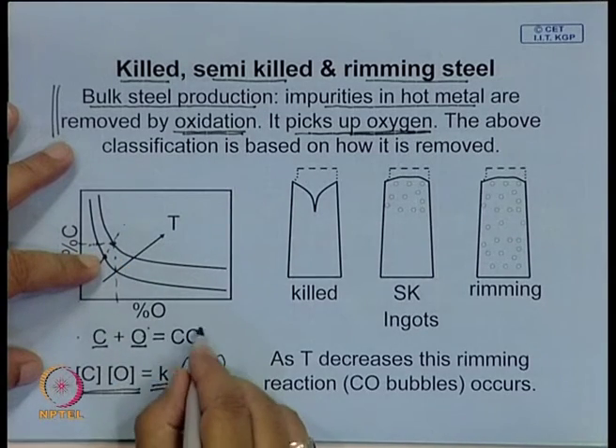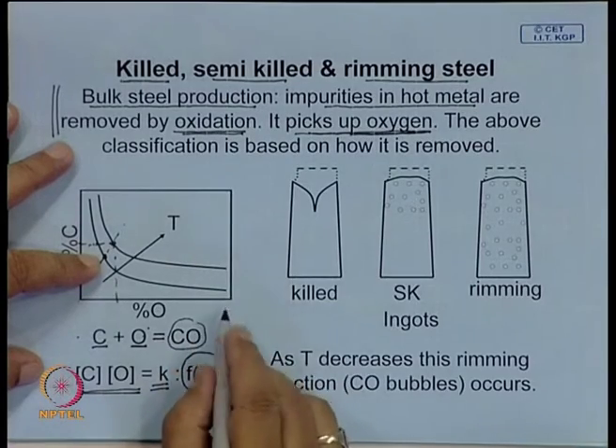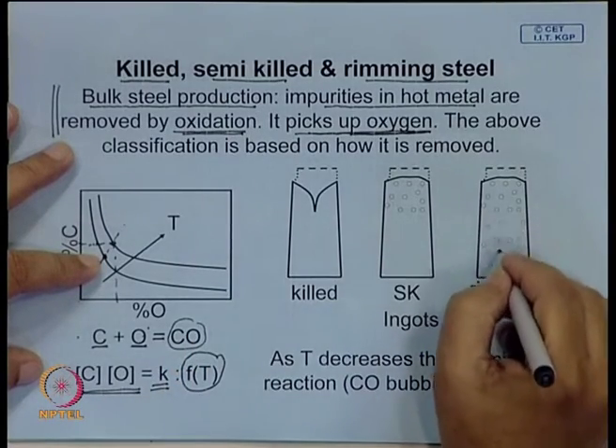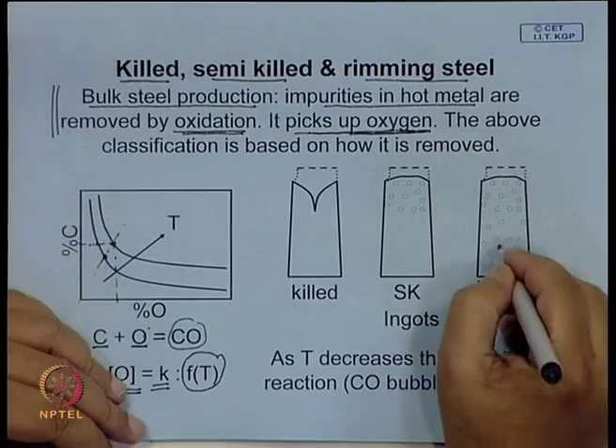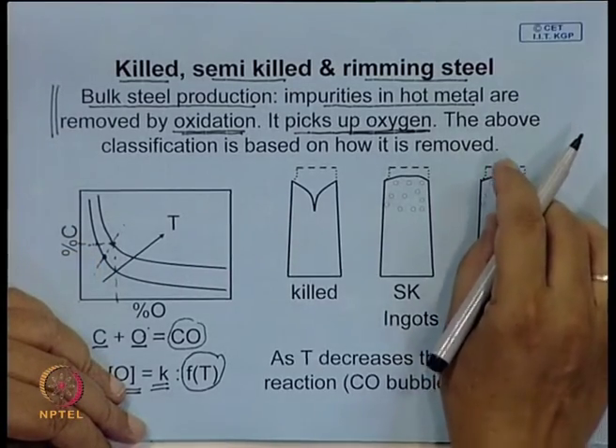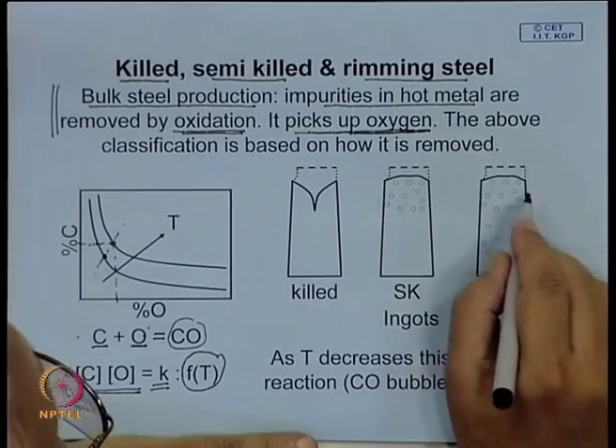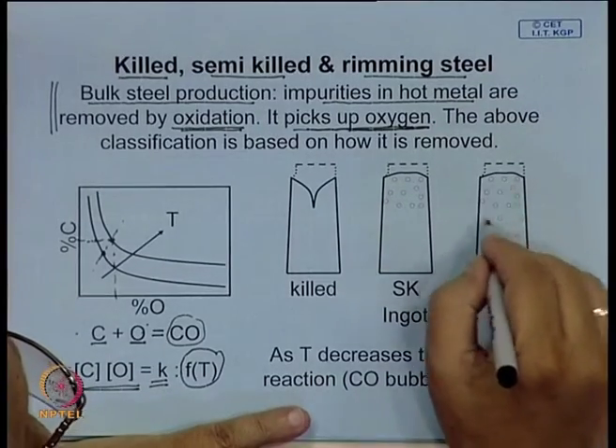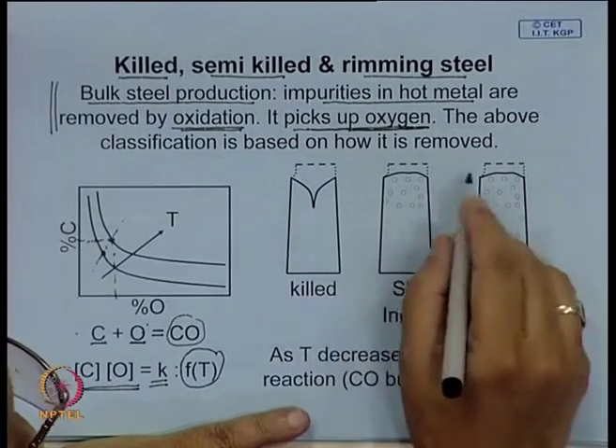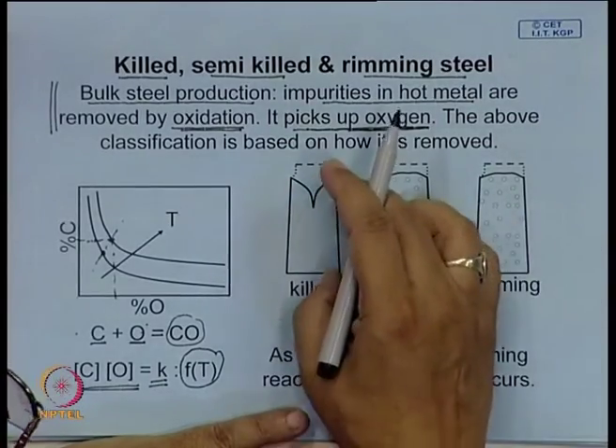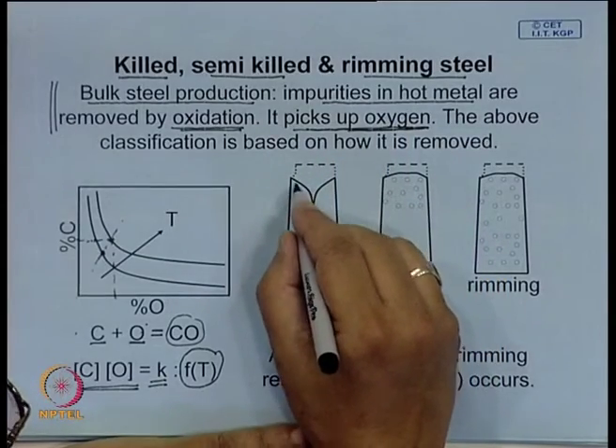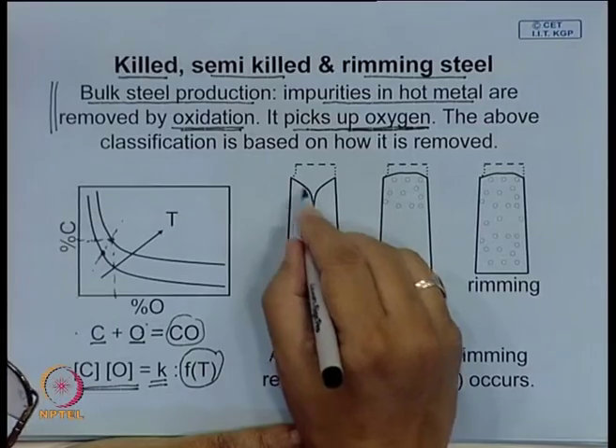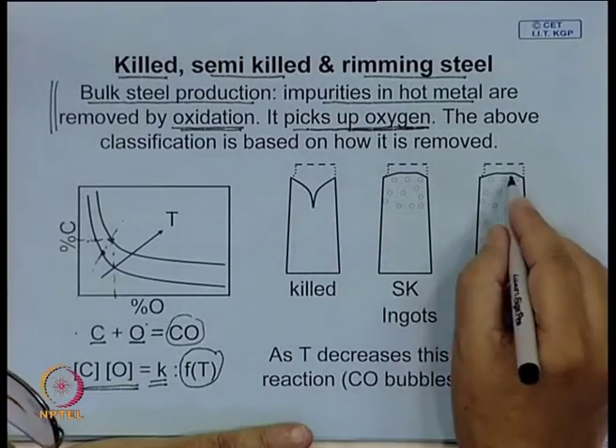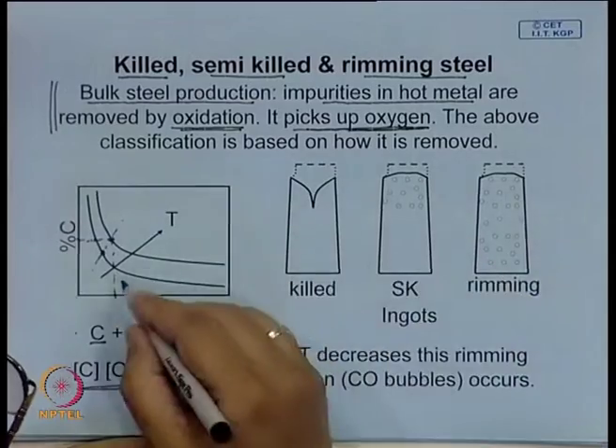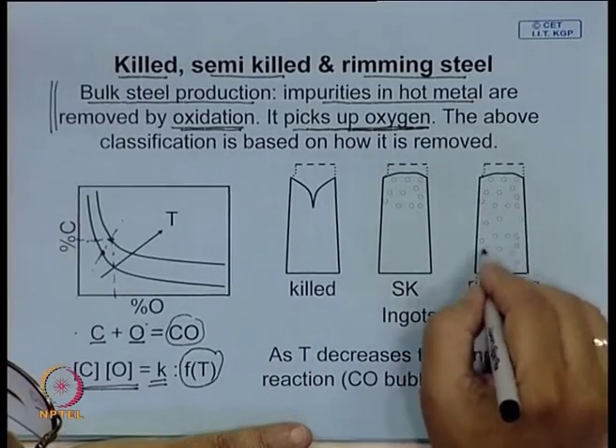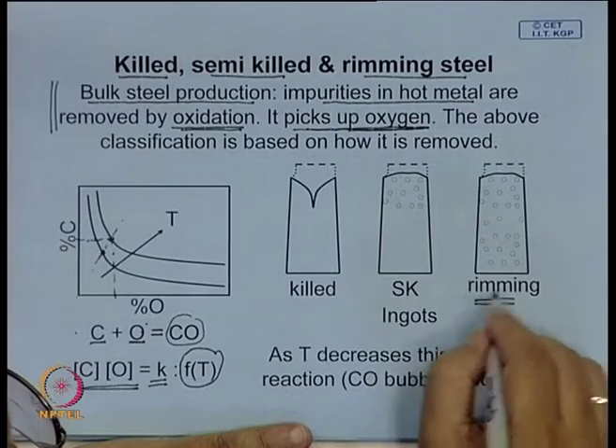That will react and form CO bubbles, and this is a vigorous reaction. The reaction is extremely vigorous and you have to control it properly. Normally, if molten metal solidifies, there should be contraction and you usually get this kind of a shrinkage. Whereas in this particular case, if this vigorous reaction takes place, it is called a rimming reaction, or rimming action.